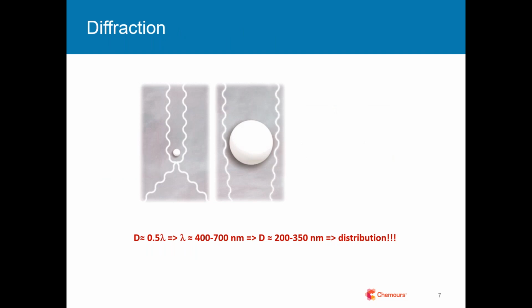That was all refraction and reflection, phenomena that play at the interface of titanium dioxide and the binder. There is a third mechanism, and that's called diffraction. That's completely different. This is a phenomenon that plays in the neighborhood of the titanium dioxide. So there's no need for the light to hit the titanium dioxide crystal, just coming in the neighborhood. And when does this phenomenon occur? That's when the light comes in the neighborhood of a particle that is half of the wavelength of the visible light, then this phenomenon is getting important.